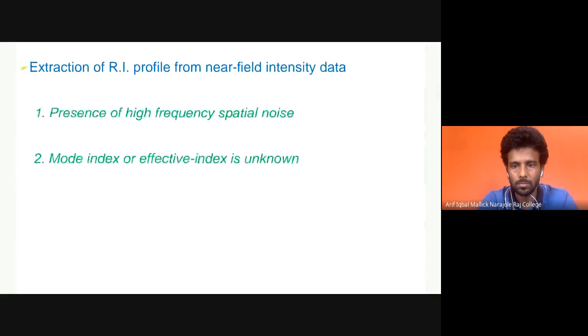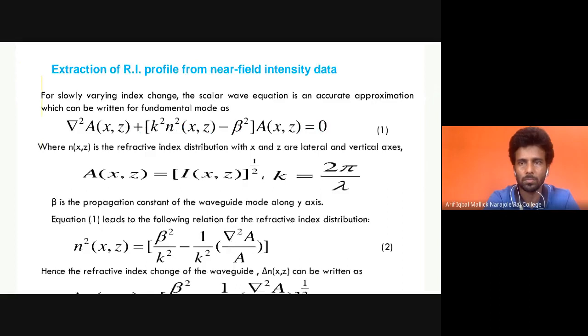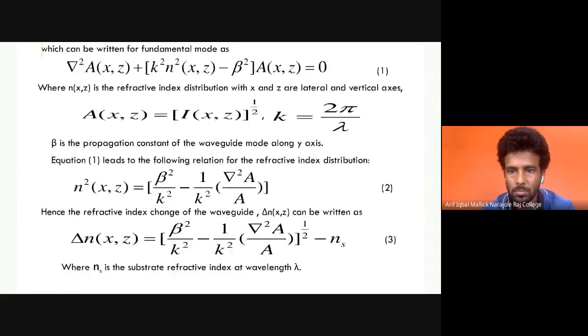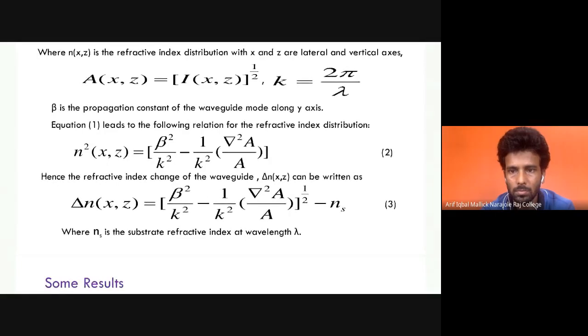Here, the experimental approach is basically extraction of the refractive index profile from the near field intensity profile. There are two problems in this extraction of the refractive index profile: the presence of high frequency spatial noise, and the mode index or effective index is unknown to us. Extraction of the refractive index profile plays a vital role in optical devices such as modulators, electro-optic devices, switches, etc. So we have to know the refractive index profile from the intensity profile. The slowly varying index change scalar wave equation is written in equation 1, where A is the amplitude, the square root of intensity. From equation 1 and the substrate refractive index NS, we obtain the refractive index change delta N, which is written in equation 3.